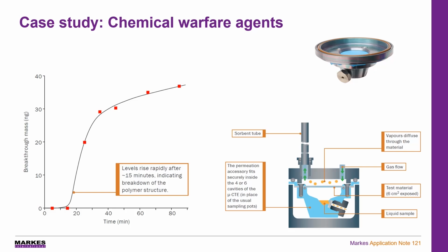Using the permeation accessory for the microchamber here allowed us to assess the migration rate of methyl salicylate, which is a simulant chemical for mustard gas, through a nitrile rubber glove. Now, permeation studies generate a lot of information on fabrics or materials associated with the breakthrough time of the chemical through the sample, the incremental concentration passing through with respect to time, leading ultimately to swelling or degradation of the sample. This type of data is very useful, especially for PPE type materials or protective coatings applied to a substrate to minimize or prevent ingress of a toxic substance.